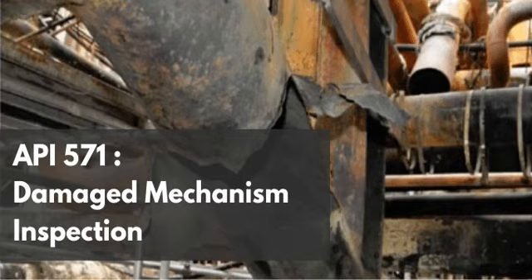Okay, let's break down the chemistry here, because the risk profile basically comes down to a very specific elemental threshold, doesn't it? It absolutely does. The alloy composition is the ultimate determining factor for susceptibility. And specifically, which element? It is the exact chromium content, the Cr percentage. Chromium, right. Remember the metallurgical theory we just discussed? The formation of that brittle alpha prime phase is driven by chromium literally separating from iron. Right, the vinaigrette separating. Exactly. Therefore, the amount of chromium available in the alloy fundamentally dictates how much of this brittle phase can physically form. So, generally speaking, more chromium equals more potential for embrittlement. In the context of ferritic stainless steels operating in this temperature band, yes, exactly.